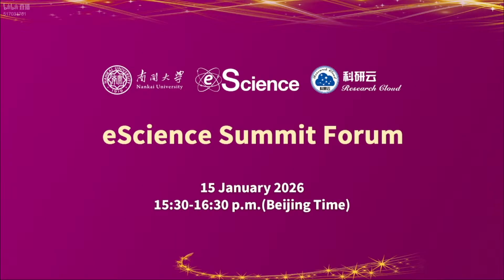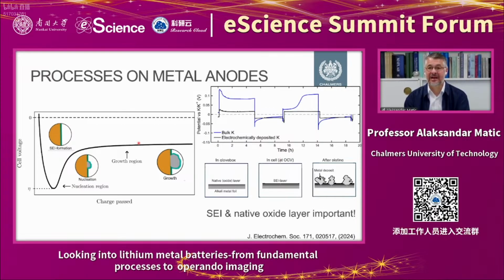And if you look at these processes, the SEI layer is very important, but also normally you have a native oxide layer on top of your bulk metal electrode, which you need to take into account. And this we showed in this work where we compared the bulk potassium electrode to an electrochemically deposited electrode. The electrochemically deposited one does not have an oxide layer. And then we can see that the overvoltage was much smaller.